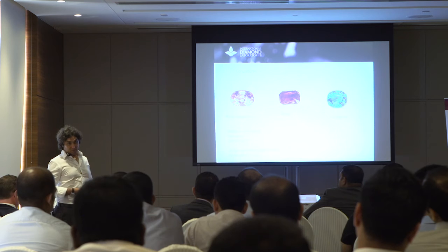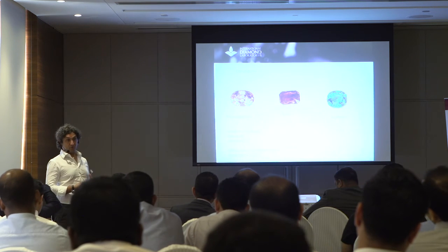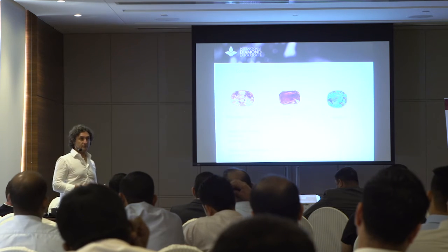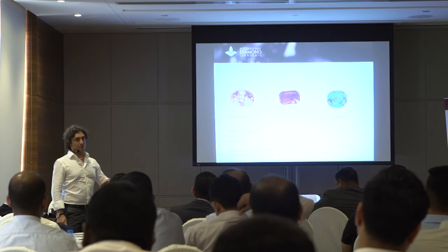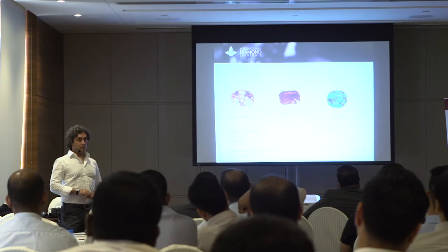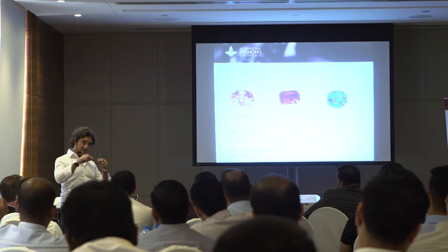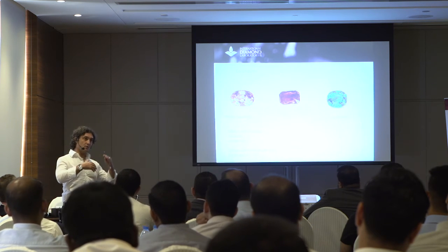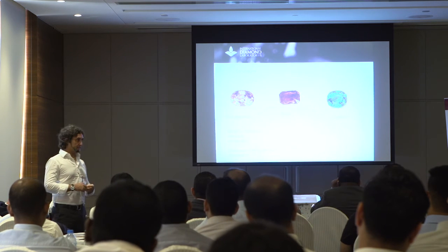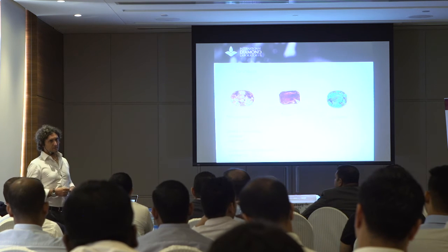Or beryllium diffusion, which was a big issue a few years ago, a very big problem, because nobody knew what they were doing. So you would have all these orange, yellow, red sapphires, which were treated with beryllium diffusion. So you diffuse not titanium, but beryllium, which will provoke this change of color. Is this a permanent change? Yes.